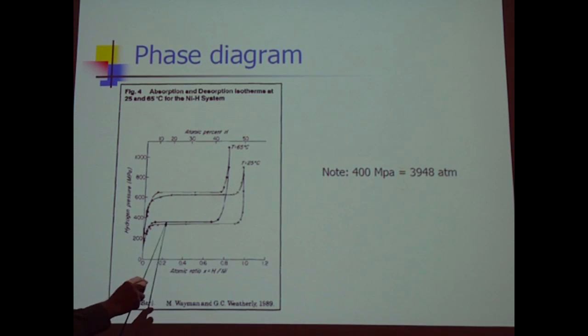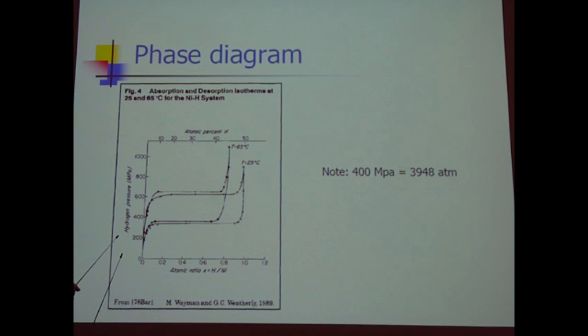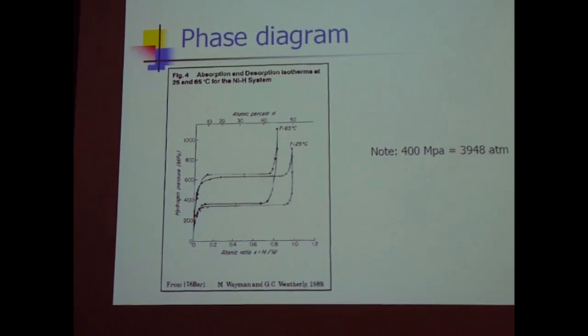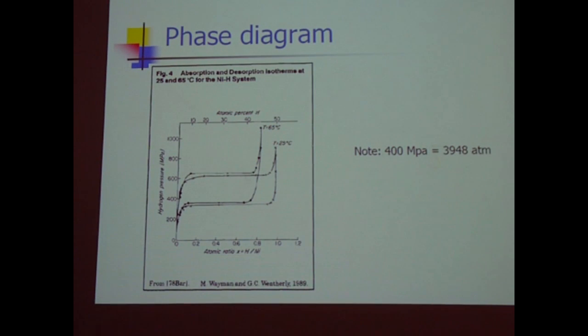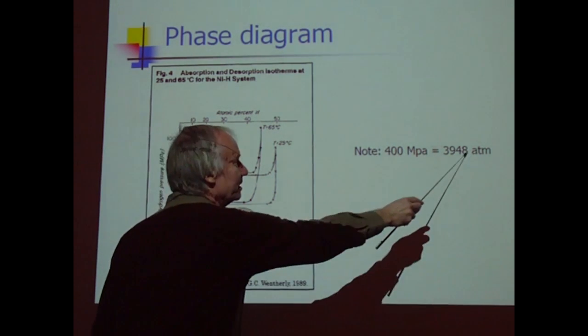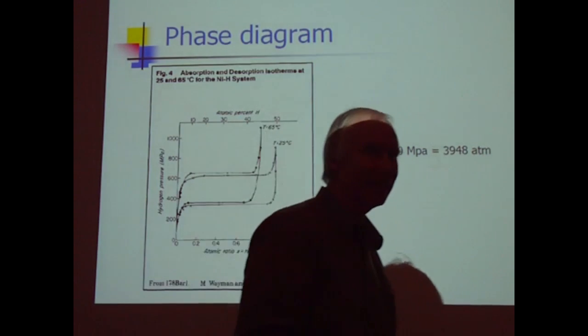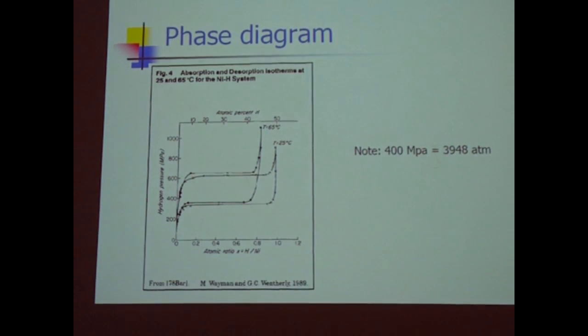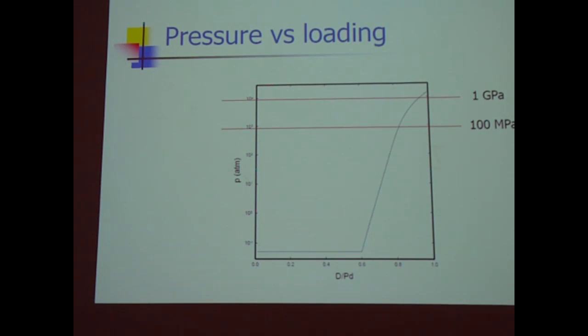We have lines going back and forth, but the pressure, instead of being less than 1/10 of an atmosphere, is 400 megapascals. And I screwed up the number before. 1 atmosphere is on the order of 0.1 megapascals, so this 400 megapascal number is close to 4,000 atmospheres. So in order to get across the miscibility gap, you've got to do some work.